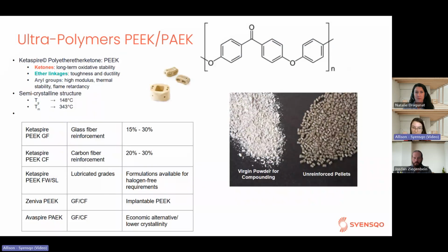And when in doubt, if those materials that I've listed can't help, if there's no other solution, we would consider our ultra polymers portfolio. These are really materials that are designed to go where no polymer has gone before, and that's when we would talk about our Ketaspire PEEK and our Avaspire PAEK. So these are the highest performing materials in our portfolio and compatible with over 1,000 steam sterilization cycles. But they offer excellent fatigue resistance and mechanical performance due to their inherent semi-crystalline structure, but also because we have a variety of fillers available. So you'll see they have a melt temperature of upwards of 343 degrees. They have ether linkages, aryl, and ketones present to increase this performance.